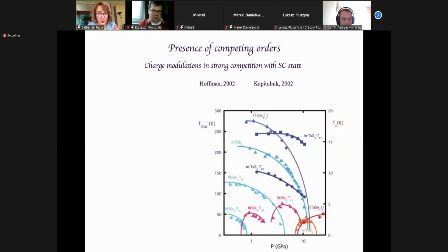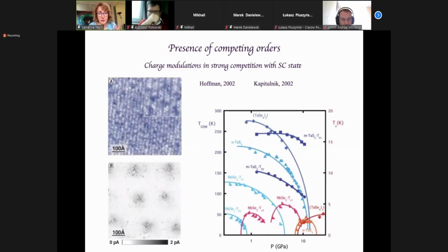So there are competing orders, charge modulation, and strong competition with superconducting states. We know that from the beautiful STM experiments of Hoffman and Kapitulnik in 2002. You do STM in these compounds and you see nothing. But what these people do is subtract 8 Tesla data from 0 Tesla data. Then suddenly, magically, you see the vortices with an Abrikosov lattice over there. Beautiful. And inside the vortices, you see the modulations.